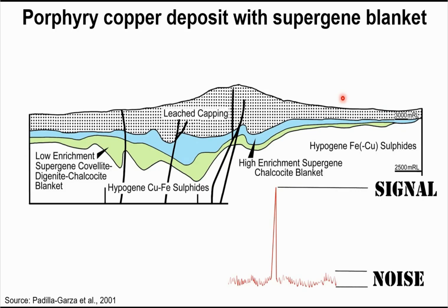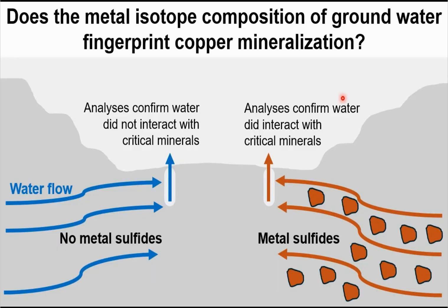So what we decided to do was to look at more than just concentration, but to look at metal isotopes, the metal isotopic composition of groundwater, to see if we could figure out whether or not there's a signal from noise. And we essentially worked with one hypothesis, which is that, as the diagram shows on the right side, if groundwater flows through and chemically reacts with copper sulfide minerals in the subsurface, we should be able to detect that chemical signal in the water that has chemically reacted with sulfides. Versus on the left, if groundwater is just flowing through barren rock, there's no signal to measure.